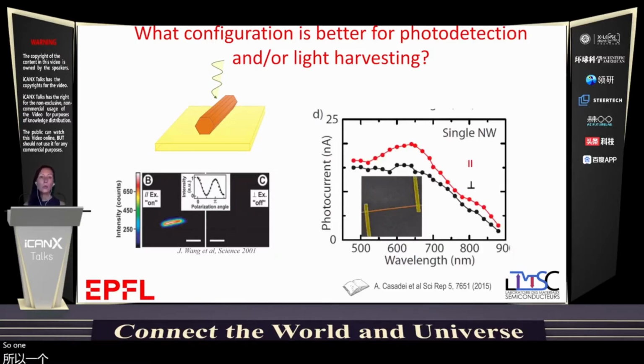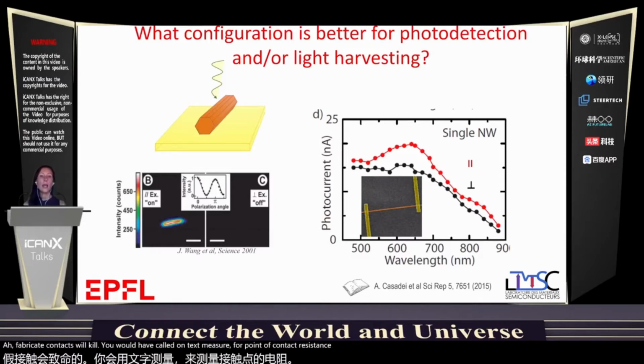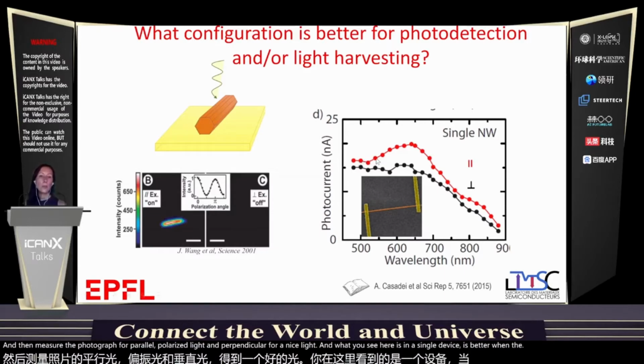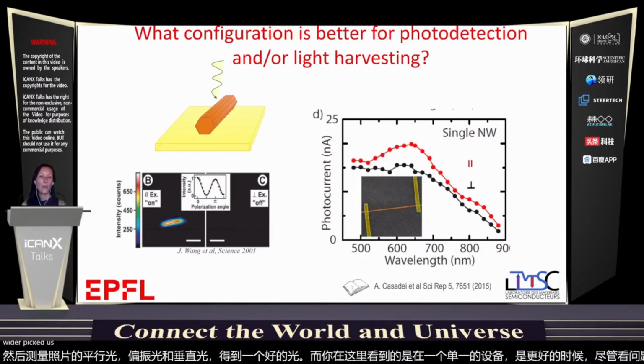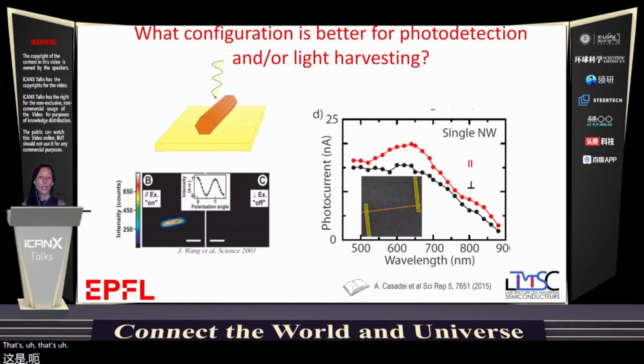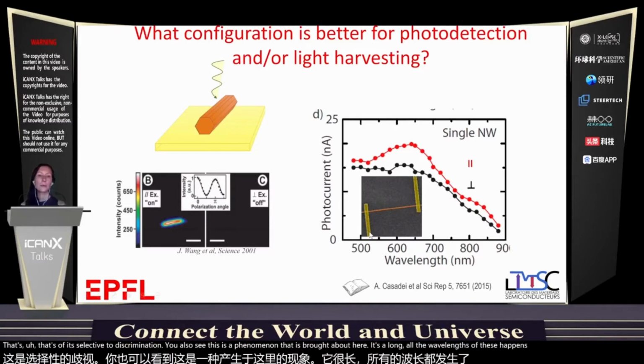So one way to also measure the absorption in single nanowires is to fabricate contacts. So here you would have 4 contacts to measure 4-point contact resistance, and then measure the photocurrent for parallel polarized light and perpendicular polarized light. And what you see here in a single device is that when the light is parallel to the nanowire, you have much more photocurrent generated in the nanowire because it's selective to this polarization. You also see this phenomenon along all the wavelengths.